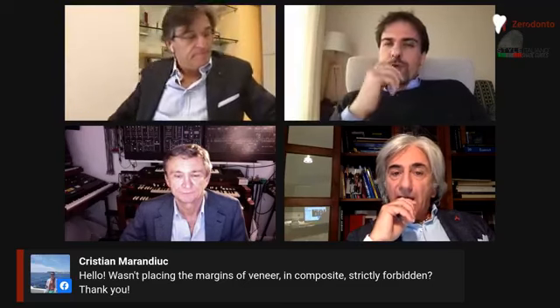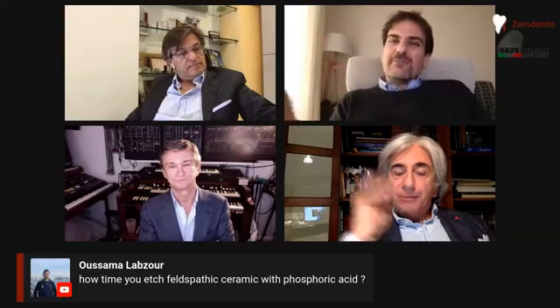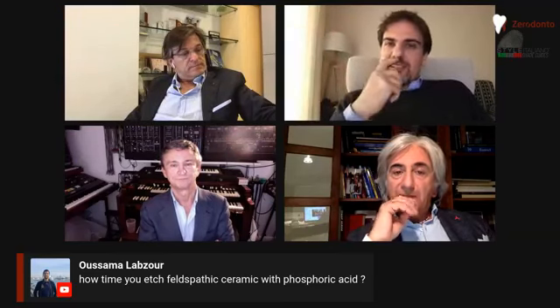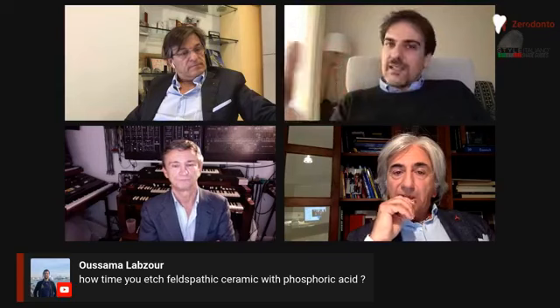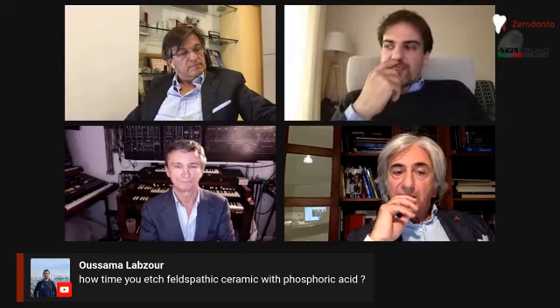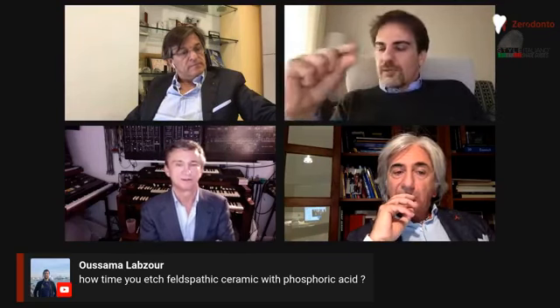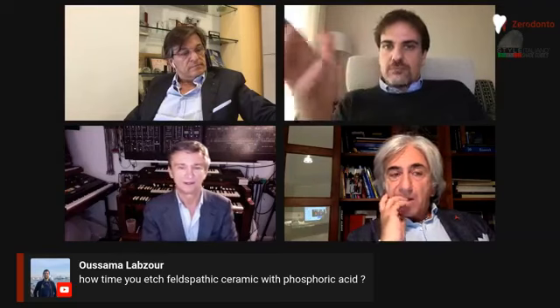If I can add just a little point, there is a very interesting paper by Murillo Gomez in Dental Materials in 2018, I guess. I showed the reference during the presentation, and they deeply discussed this point, because the use of phosphoric acid just for cleaning is advised by most clinicians, but there is a little lab evidence that it could be slightly detrimental. But it's a very common clinical practice as well, to remove the possible little remnants after degrading. So that is the point of Professor Putignano.